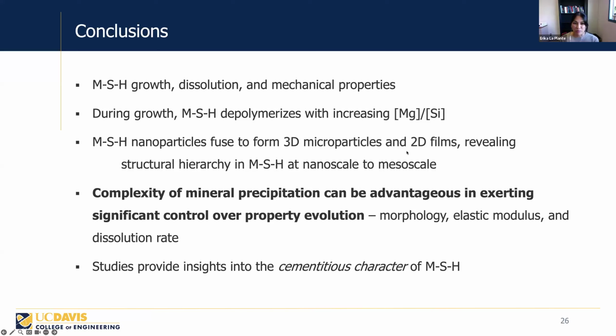And it also turns out that mica is a phyllosilicate. It is similar to MSH structure. So when we look at the elastic modulus, that means that it would have a similar interaction between the tip and the mica and the tip and the MSH. That also increases the robustness of our measurements of the elastic modulus. Yeah, that's fantastic. Such an interesting approach. Moving on to some other questions here.